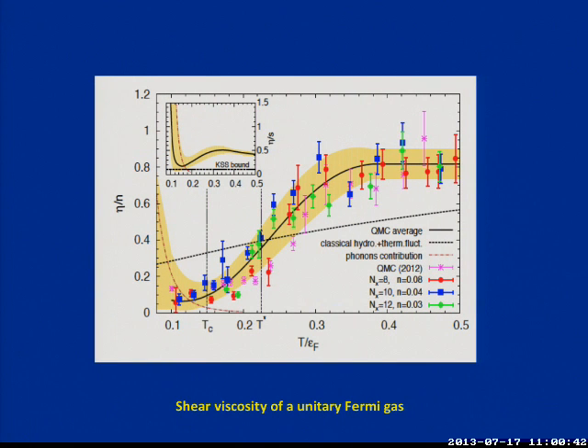viscosity. As a function of temperature, it goes like this. The critical temperature is here, and you see there is a significant dip. Now there is a region here which is yellow. At very low temperatures, the superfluid thermodynamics is dominated by phonons. The cutoff in temperature depends on the size of the box, because obviously the lower the temperature, the lower the energy of the phonons, and we don't have a big box. So we had to include the contribution of those phonons from theory. There is an effective field theory of phonons in a superfluid, and their contribution is this one in yellow. So we added it, and this is what comes on top of our results.